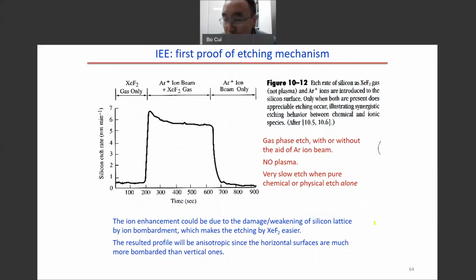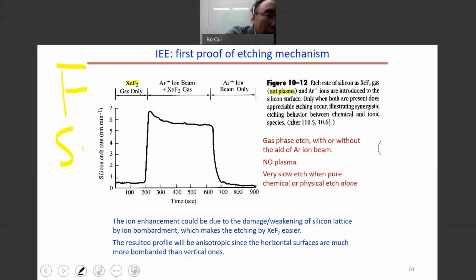So this is the first example of the ion-enhanced etching mechanism. In this case, we have two gases. The first one is xenon difluoride. There is no plasma, it's just this gas. We know that this is a noble gas fluoride, and this compound is not very stable. On the silicon surface, it will generate fluorine. This fluorine will react with silicon to form silicon tetrafluoride. But the etch rate in this case is not very fast. It's only half a nanometer per minute.